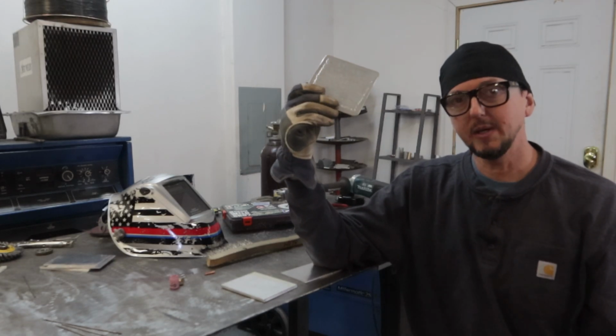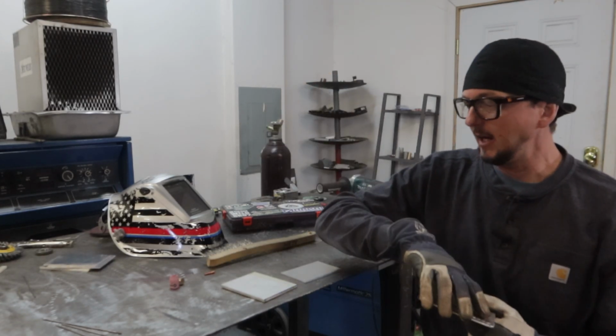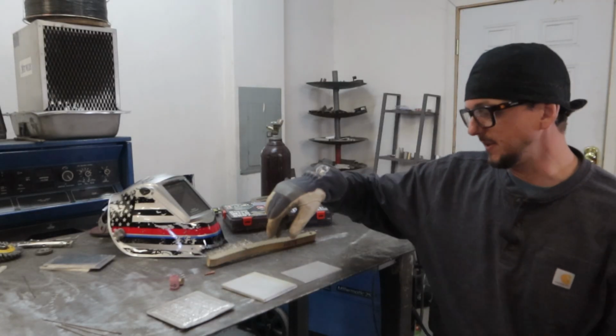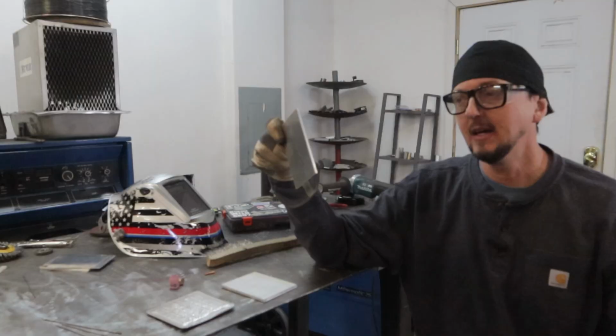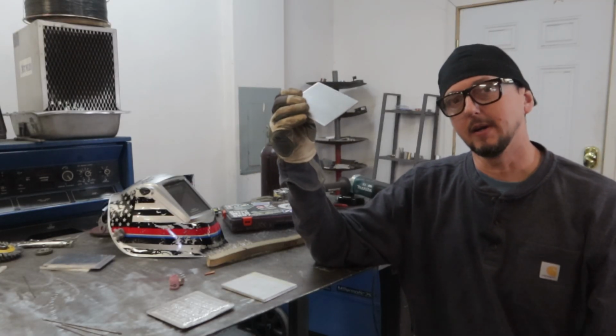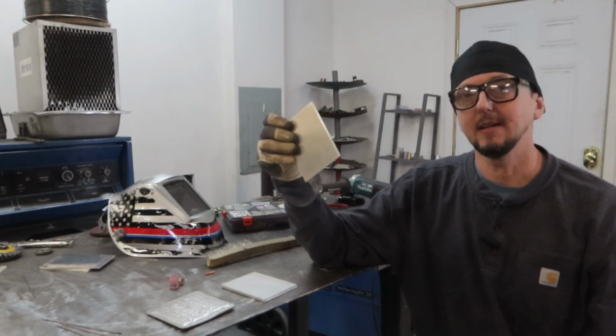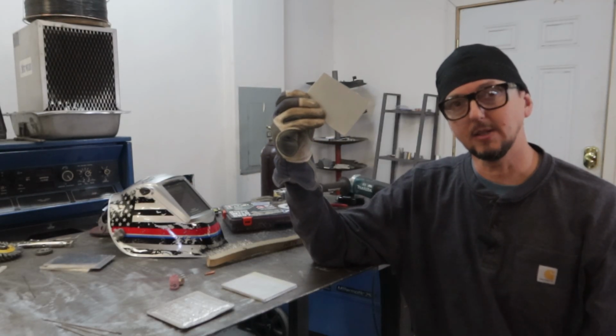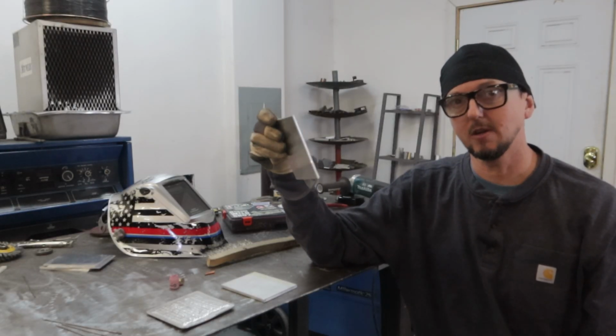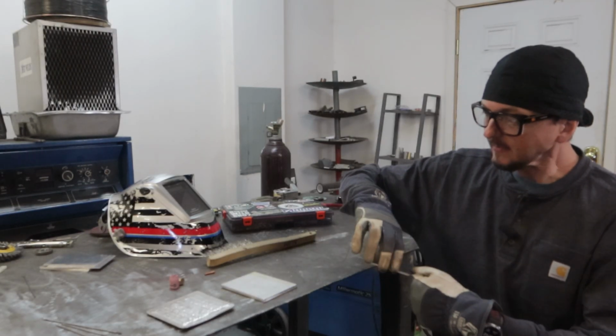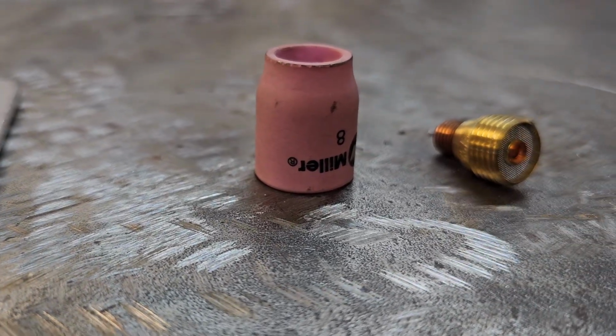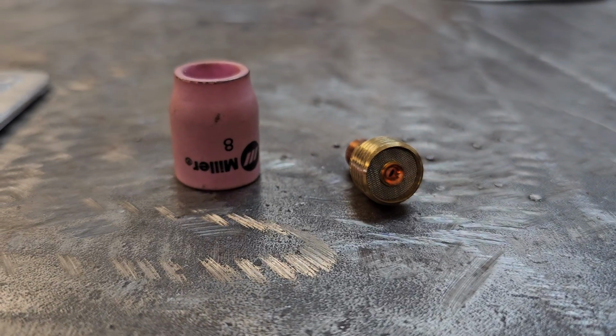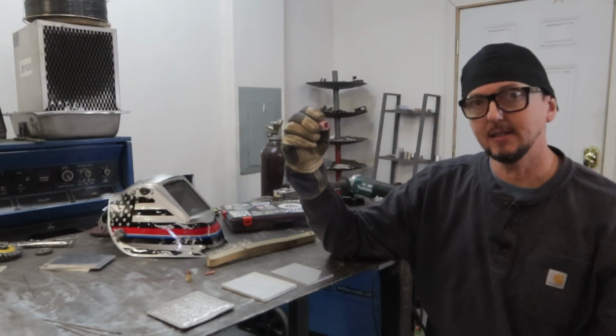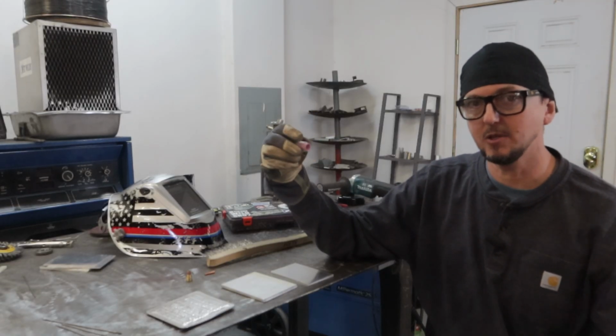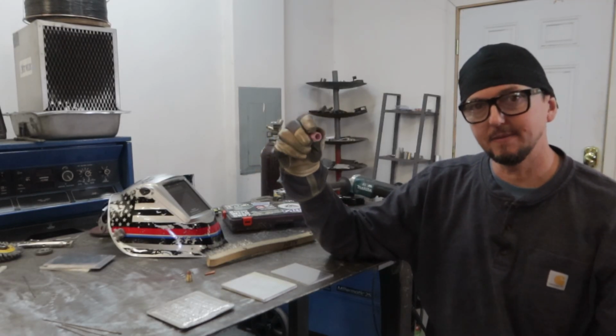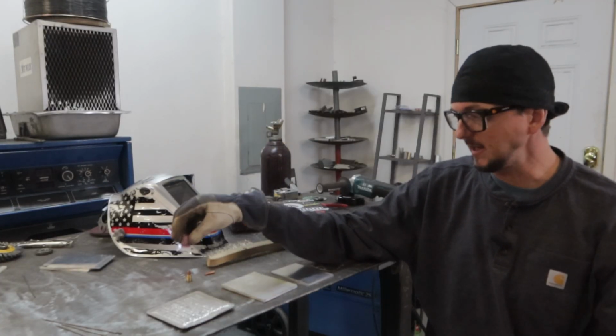So the first thing that we need to do is properly prep the material. Aluminum is a very reactive material, so it's going to be very susceptible to contamination just on the surface of the material, or if our shielding gas isn't efficient enough. So we need to do a good job of cleaning the material and making sure our shielding gas is efficient. For this, today I'm going to be using a gas lens setup with a size 8 ceramic cup. This depends on what size material, how much amperage you're using, all that kind of stuff. But for this particular project, that's what I'm going to be using.